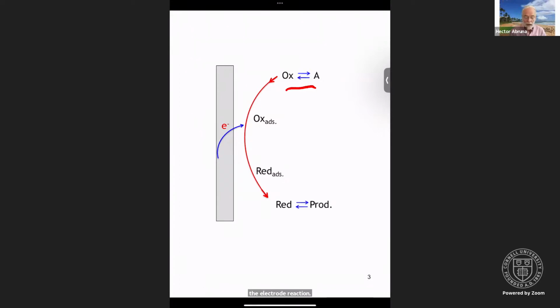And then you'll see the arrow, it goes from Ox to Ox adsorbed. By that we mean that this species will feel the presence of the electrode potential, meaning there's an intimate interaction between the electrode and that species. That typically means that chemical species will be just a few angstroms or less than a nanometer from the electrode surface. As we'll see later on, the distance over which an electron can transfer is probably less than a nanometer or so at reasonable rates.